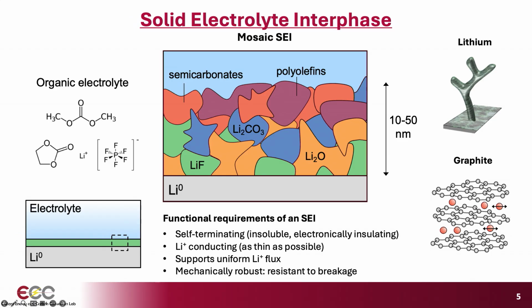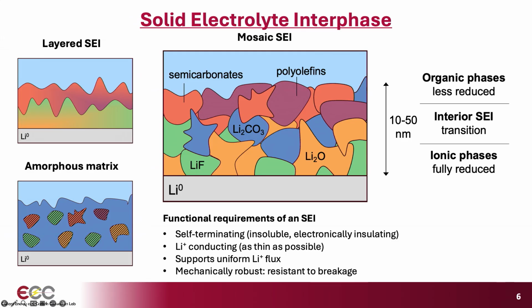It forms an SEI, and that was actually essential to the commercialization success. However, the SEI, I would say, has less demands placed upon it because graphite undergoes far less extreme volume changes during its cycling. Okay, so getting the lithium SEI just right is really challenging, and it really remains a grand challenge in the field. So because the SEI is derived from the electrolyte, every time we change the electrolyte formulation, we have a different SEI that we have to understand.